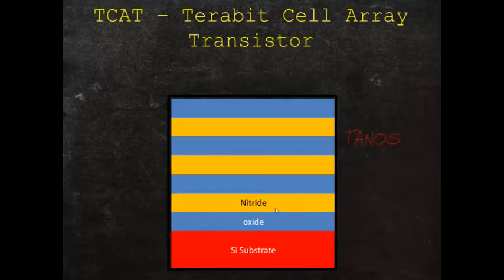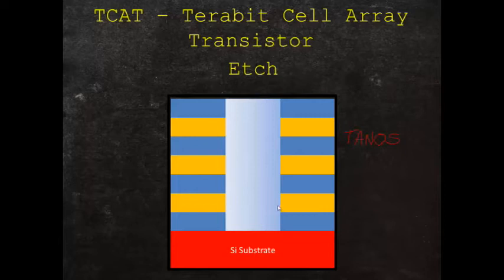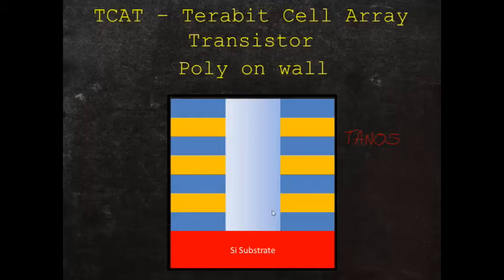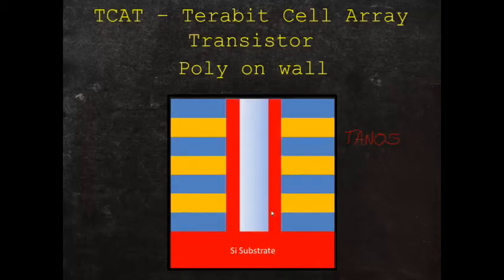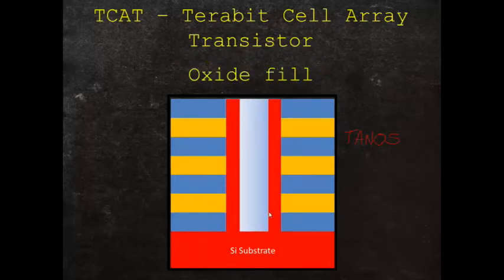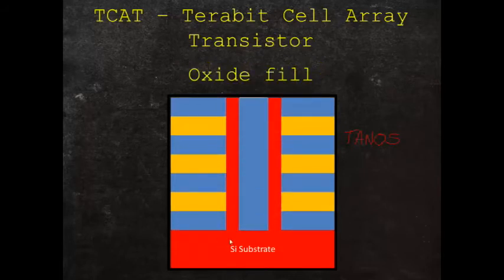The next step is the same as BICS, where you etch a hole down through your stack. Here the hole is lined with polysilicon. We're not using the nitride oxide layers like in BICS, so this is different. We put the polysilicon on the wall. The silicon dioxide is then used to fill the hole. This is supposed to get better subthreshold characteristics than a solid core of polysilicon. Now, we go on to make the gate.